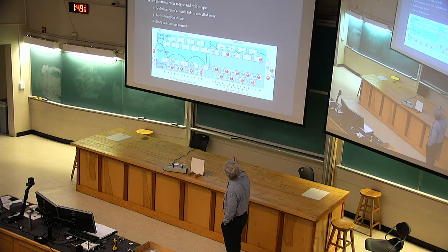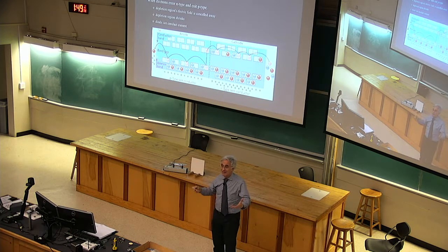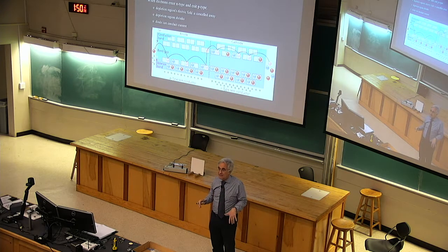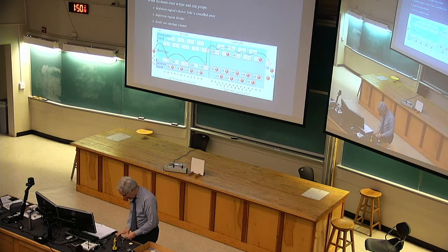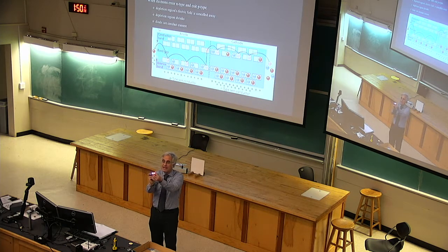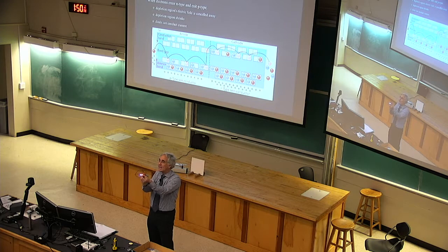And when they drop, they go in here. Once they get across the junction and make the step from up here to down here, that's a step in energy. They're shifting from one quantum wave to another. In a conventional diode, they create heat because their energy is released. In a light-emitting diode, the whole point of the story, they emit light. So what you're seeing in these light-emitting diodes is electrons pushed in on the N-type semiconductor side, migrating across the junction, and then shifting from a conduction level to a valence level and emitting light in the process.